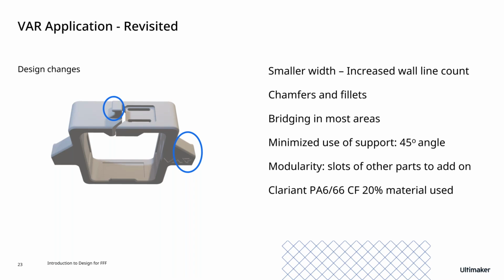45-degree angles were used in most places to reduce the amount of support usage. You can see some slots on the inside of this part. We have separate 3D printed parts that go in there. I will talk more about that in the next slide. This part was oriented such that the logo on the right was flat on the bed. And lastly, we used a third-party Clariant PA6/66 material. It's a composite with a 20% carbon fiber infill for higher strength. Let's get into a little more detail here.